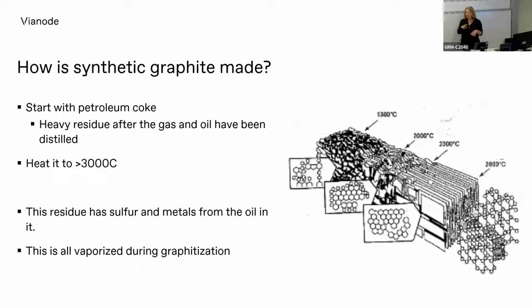It's the highly aromatic stuff with all of the different kinds of materials in it. But unfortunately, because it is the bottom of the distillation process, all of the metals and the sulfur and things like that that would have been in your gasoline end up in the coke. Over time, there have been more and more requirements around fuels that people will use for internal combustion engines to have lower sulfur content, lower metals content, so that you can make those cars greener. But you can't just make oil have lower sulfur content or lower metals content. So that material ends up in the petroleum coke, which is what we use to make synthetic graphite. So if you have an open furnace where you are making your synthetic graphite, all of those elements are coming out into the area around your furnace.